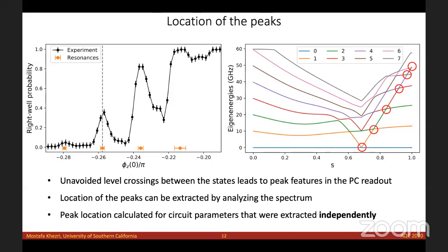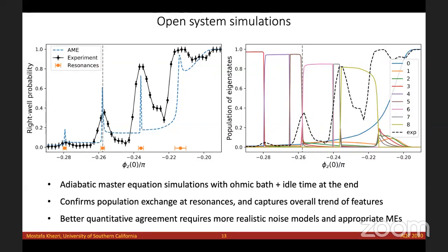And we could also more or less confirm this model by performing some adiabatic master equation simulations, which you can see as these dashed blue lines, which qualitatively capture all the behavior of these peaks. It's missing the width of the peaks because we're using high frequency noise, which we know is not true for most superconducting circuits. And then also we're looking at the eigenstate populations of the circuit. We can see that exactly at the locations of those peaks where we were expecting population transfer to higher states, you're observing those population transfers to higher eigenstates of the system.